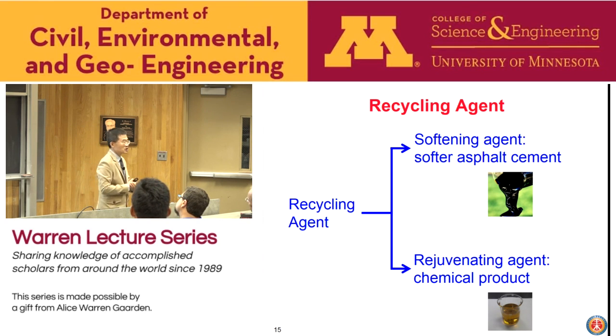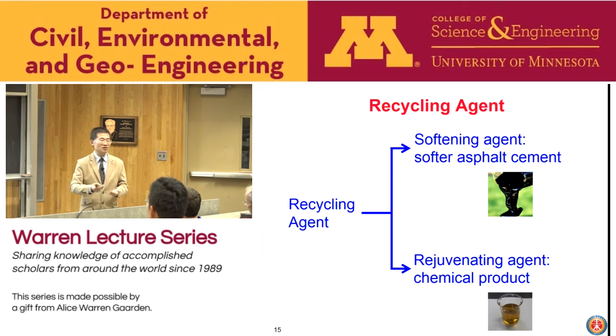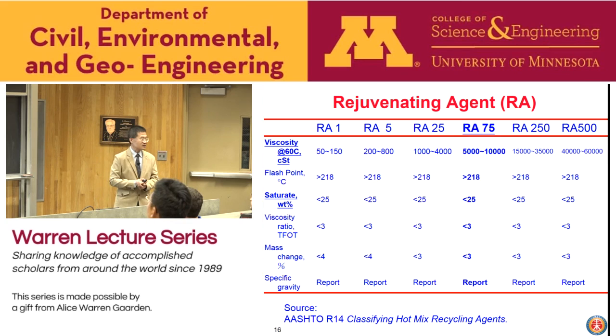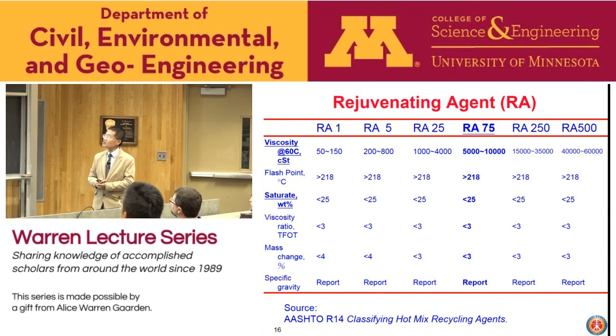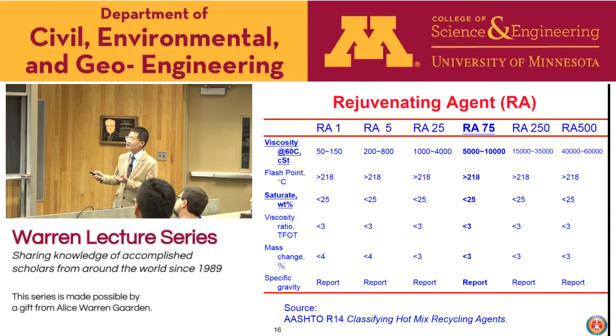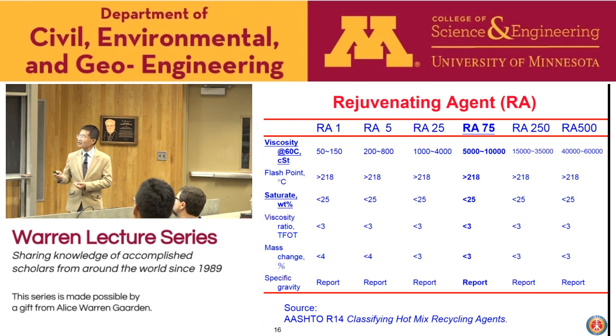But in Taiwan, we still use traditional viscosity grading systems. So we use AC10 as a softening agent instead of AC20. The rejuvenating agent here is a chemical product aimed to restore chemical and physical properties of asphalt cement, of aged binder actually. This table provides the specifications of rejuvenating agents according to asphalt classification. In this study I'm going to present here, we use the RA75 with the viscosity value ranging from 5,000 centistokes to 10,000 centistokes at 60 degrees Celsius. So that's the rejuvenating agent.